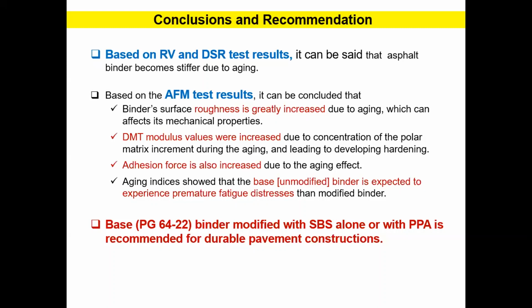Also, the adhesion force increased due to the aging effect. Moreover, the aging indices showed that the base binder is expected to experience premature fatigue distresses compared to the modified binders evaluated in this study. Finally, it can be recommended that the base binder modified with SBS alone or with PPA can be used for durable pavement constructions.